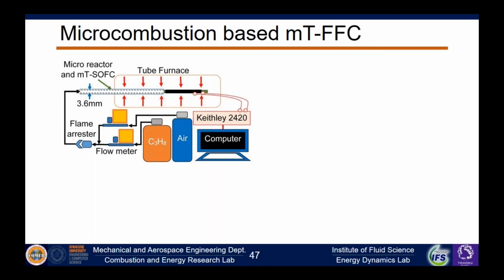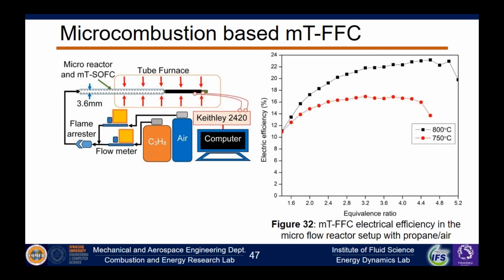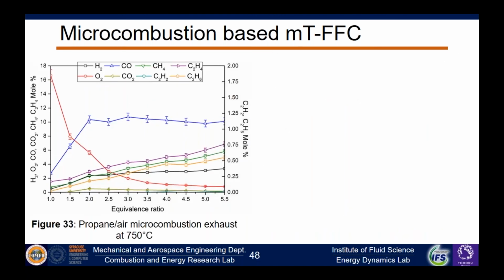We used propane in this case. Methane has some reactivity issues. Because of the way the molecule is, it's very hard to break a C-H bond and break methane down, so you actually have to get well beyond 900 degrees, and there are some sooting issues there that I won't get into too much, but I'm happy to answer any questions. So for this initial study, we used propane as an example. At 800 degrees Celsius, we saw over 20% electrical efficiency. We were able to convert over 20% of the chemical energy into electrical energy in this setup, but we had to get fairly high equivalence ratios to do it. So there are opportunities here. Combining microcombustion with this simple setup and pushing beyond the upper flammability limit, we might be able to approach electrical efficiencies that are very reasonable and could have real opportunities in many other applications.